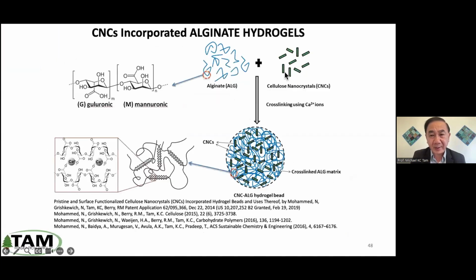We take this nanoparticle, and then we want to build a structure that we can scale into a process. So we take cellulose nanomaterial that we can modify the surface of, and then we mix it with alginate. As you know, this is seaweed. Then we extrude it into a calcium solution, and we get physical cross-linking. Now these nanoparticles are trapped within a porous structure. These porous beads can be from 1 millimeter to 10 millimeter, and can now be put into a column, and then we can do remediation of this water in a very straightforward way.